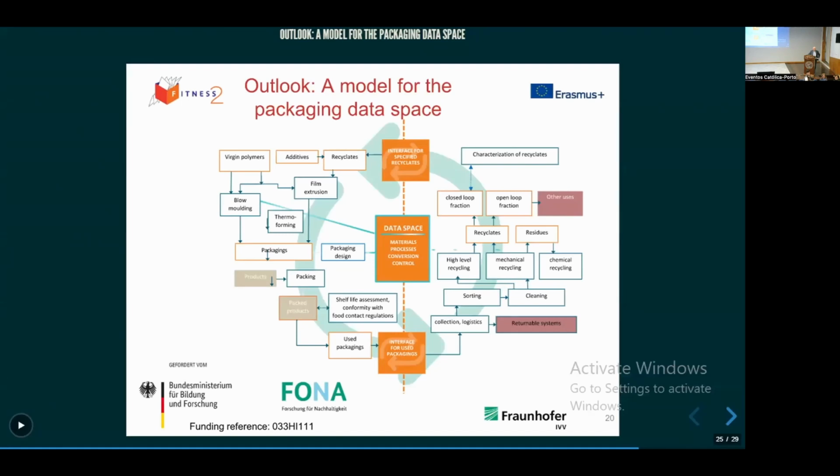Okay, this is me. Thank you for your presentation. I'm really happy to see someone else working on functional barriers. There is a problem with functional barriers also, is that as soon as the recycled material is in contact with a functional barrier, the contaminants that are in the recycled material start to migrate. And for example, when I buy my packaging, I don't know when it has been manufactured. So do you think there is a way to control this, to control the span life of a functional barrier and be sure that when I buy my packaging, it's not already too much contaminated?